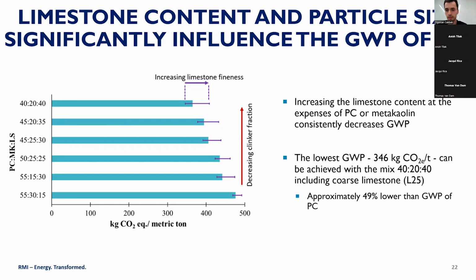So the lowest global warming potential in this figure was achieved, for example, with the mix 40-20-40, which means 40% Portland cement, 20% calcined clay, and 40% limestone, including the coarsest limestone I had in my experimental matrix, which was approximately 49% lower than the global warming potential of Portland cement, according to our calculations.